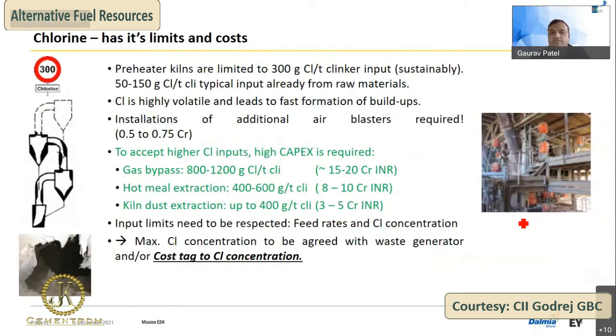Chloride, yes, we are maintaining a chloride limit. The global standard is 300 grams, but we are slightly higher, around 400-500 grams chloride per ton of clinker. Chloride has the disadvantage of blocking our cyclone bottom stage. So to avoid the chloride, there are three systems available. One is the proven technology, gas bypass, around 15 to 20 crores of investment, and we have been planning to install it in 2 of our locations.